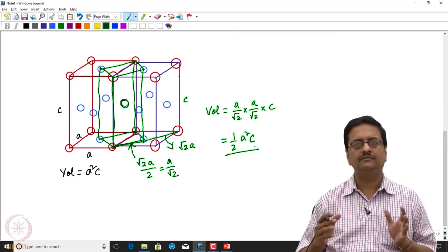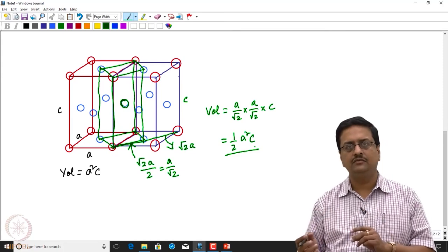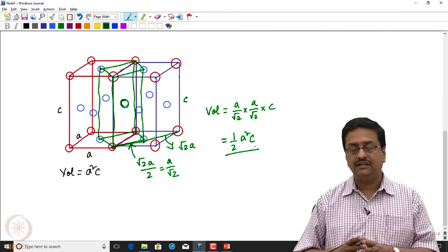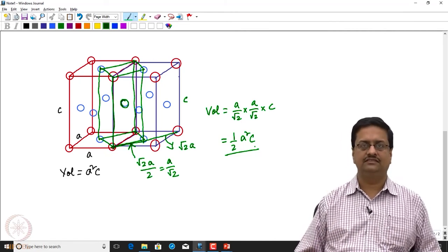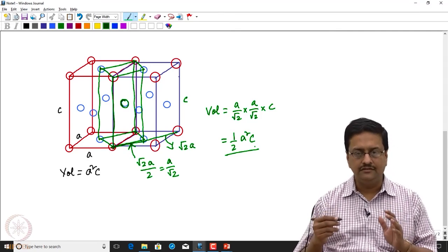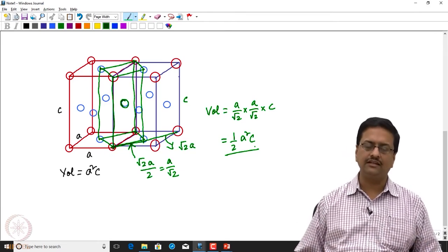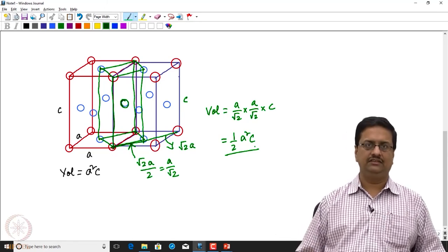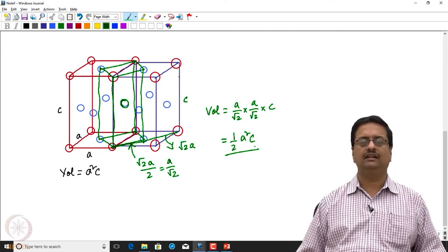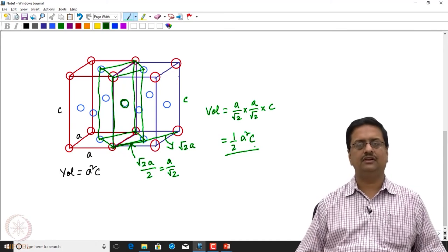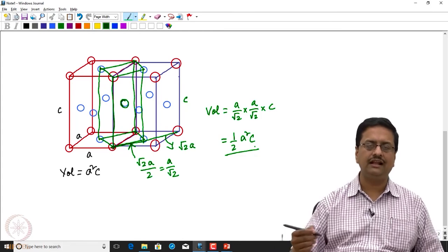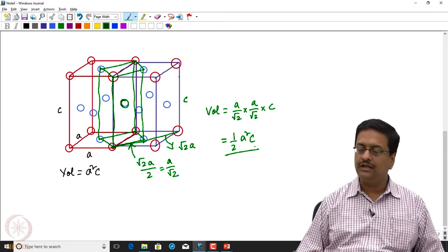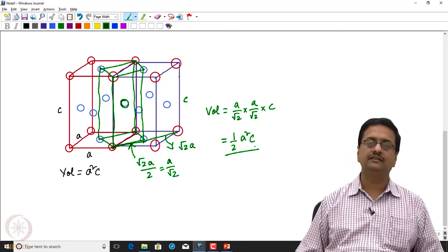So, when we have possibility of representing same crystal structure using a smaller volume, we should use that as the basic lattice instead of the one which has a higher volume. And this question arises every now and then when we try to index a crystal system. We should always look at the unit cell parameters and the volume of the lattice that we are getting from a crystal data and see which is giving you the lowest volume with highest symmetry. So, suppose if there are choices between two different tetragonal lattices, we should choose the lattice which has the smaller volume. If we have a choice between two different symmetry lattices, then we should choose a lattice of higher symmetry than a lower volume. So, this is where we need to make a decision what lattice should be chosen at the beginning of any crystal data collection.